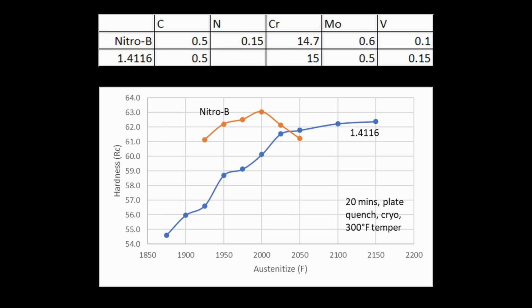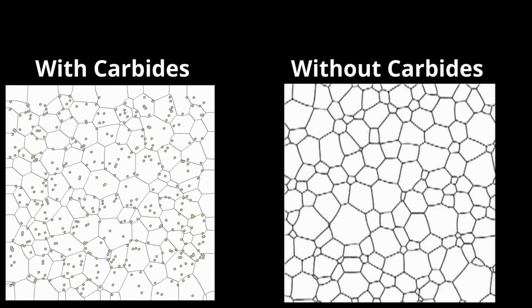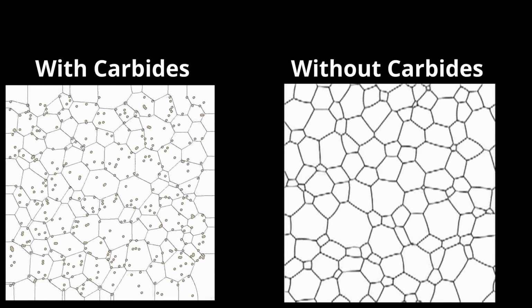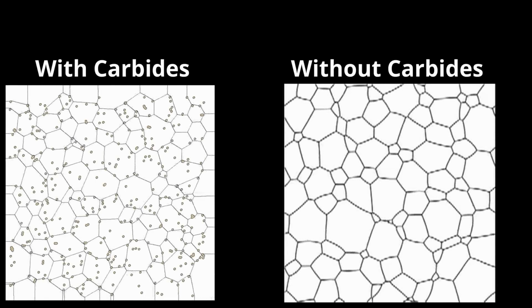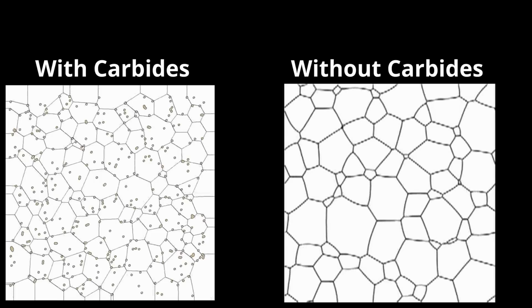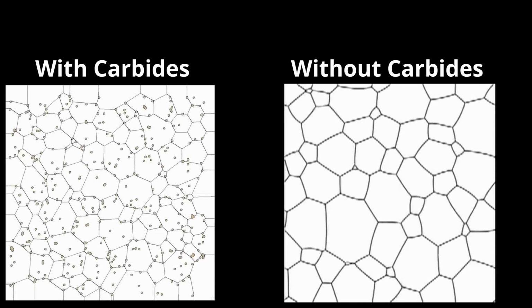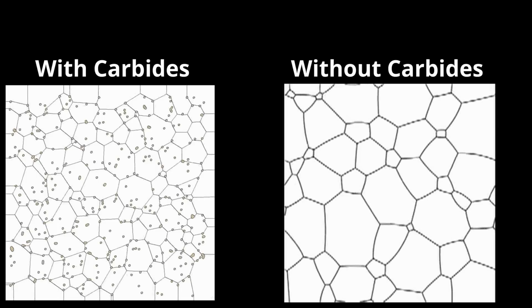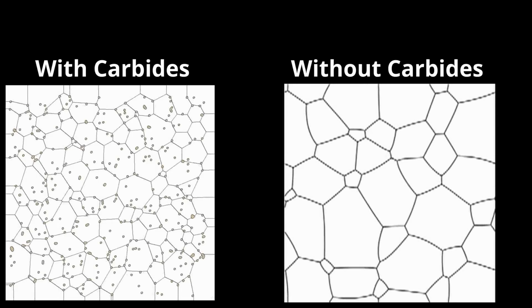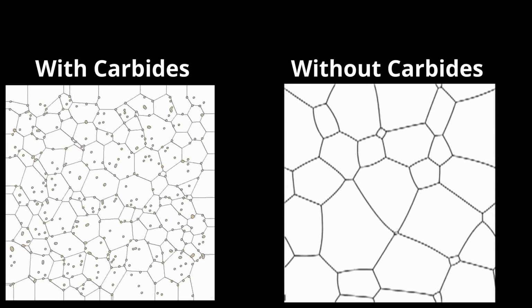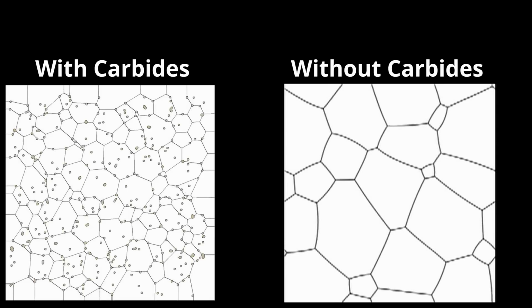The other issue is if we're dissolving all of the carbide out of the steel, putting everything in solution, there are no carbides left to pin grain boundaries, which means that grain growth is very rapid, especially at these temperatures we're looking at, like 2050, 2100. Grain growth is pretty fast up there. So you'd be blowing up your grain size and having very brittle steel.